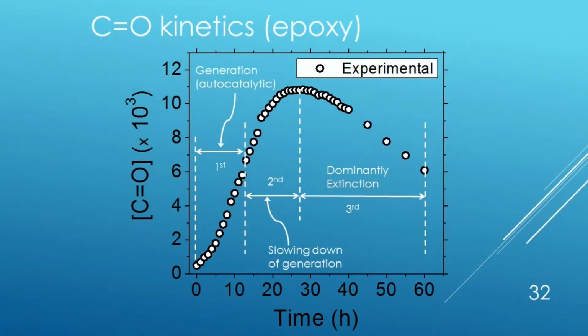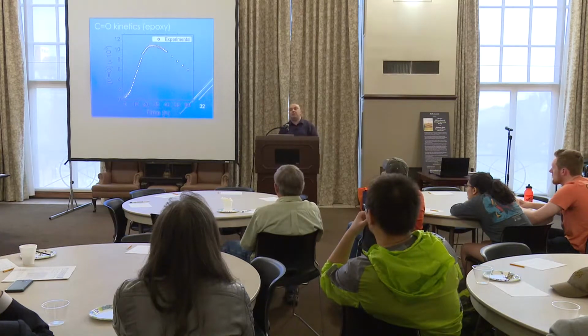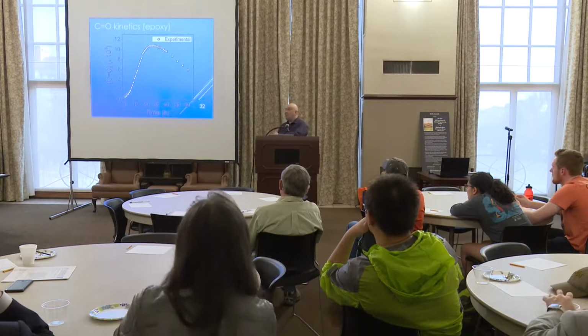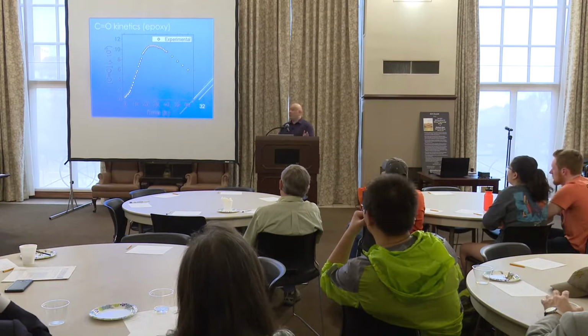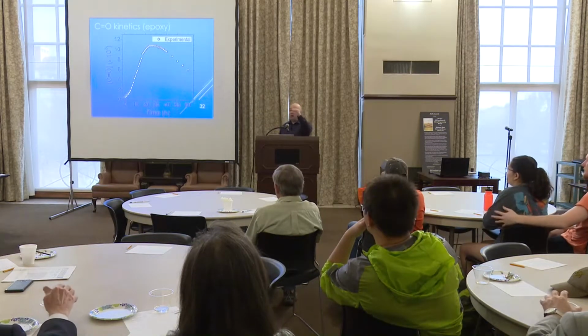Okay, so what we did was, we integrated the area under that curve to quantify the amount of carbonyls. So by time, this is the kinetics we derived for photodegradation. This is the carbonyl density as a function of time. And you see here some sigmoidal behavior, which is a curve in the form of an S. That means it first gets faster, and eventually it saturates. It's just like bacterial growth. Bacteria are producing themselves, but eventually they saturate because the food source is limited. Here, eventually the system gets to a maximum because all oxidation sites are depleted, and then it goes down. The carbonyl density is decreasing.